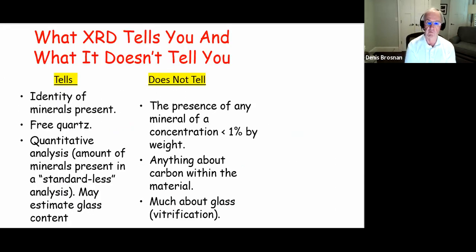Well, just like XRF, X-ray diffraction, XRD, tells us certain things, and it doesn't tell us certain things. It tells us the identity of the minerals present above a concentration of about 1 weight %. It tells us free quartz, but it doesn't tell us much about glass that may be present. Now, those familiar with X-ray diffraction know that there are some low angle X-rays diffracted by glass, and the amount of glass can be estimated by modern up-to-date machines, but it doesn't tell us much about the glass. It can be used in quantitative mineral analysis. That makes it very useful in comparing chemistry to mineralogy.